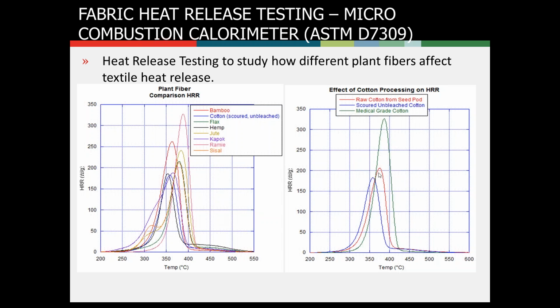So the raw cotton from the seed pod has this level of flammability. If you remove just those base oils, the flammability goes down, so it's actually even less flammable after you treat it from the raw seed pod. But if you bleach it and scour it for medical grade, then the flammability goes up. And that can be explained by some of the chemical functions of that fiber. So this technique can be very useful for screening through different types of fiber sources prior to weaving them into a fabric and then considering them for a flammability application.